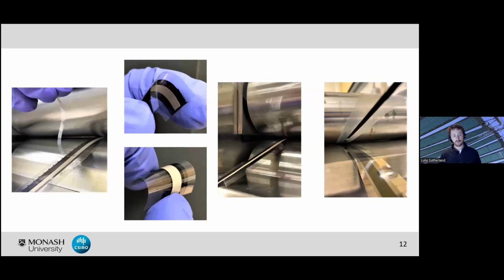However, one clear limitation of using the calender press is that without significant automation or precise control of the distance between our two calender press rollers, slight variations in the thickness of our carbon electrode or of our underlying device stack will lead to variations in the pressure being applied in our lamination process, and subsequently impact the performance. What's more, we wanted to then demonstrate this technique for larger area devices, and with our calender press, uneven pressure distribution across the surface area of our carbon electrode will again result in poor performing devices. And finally, we wanted to demonstrate this technique for rigid glass-based cells, which, as you could imagine, would simply break if we tried to put these through our calender press.